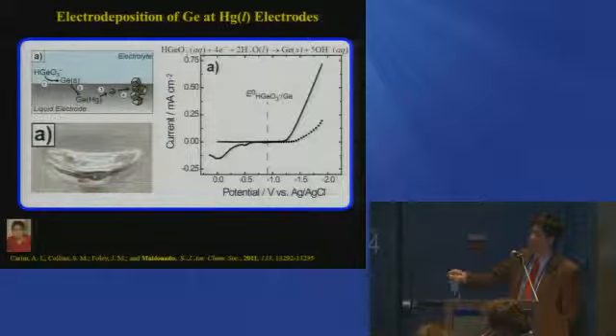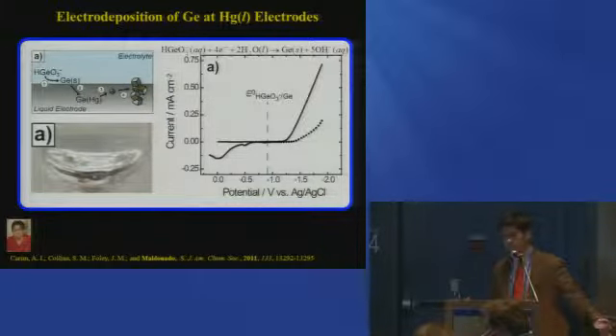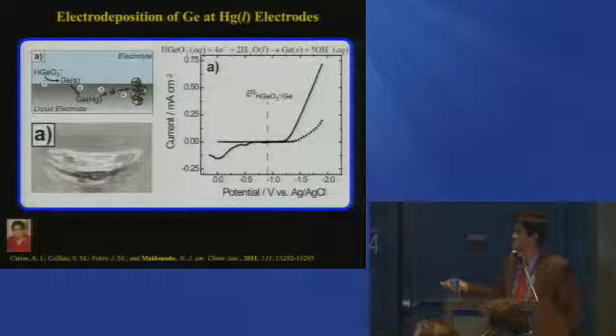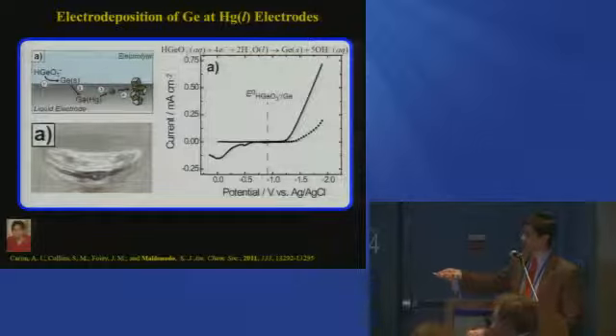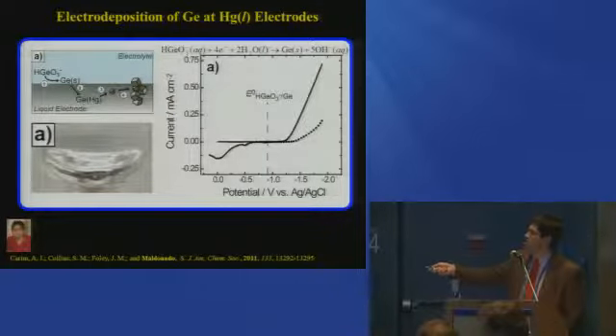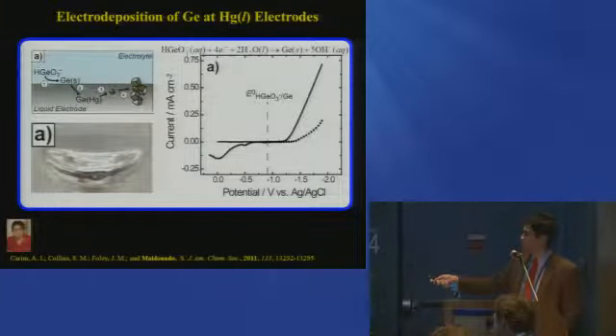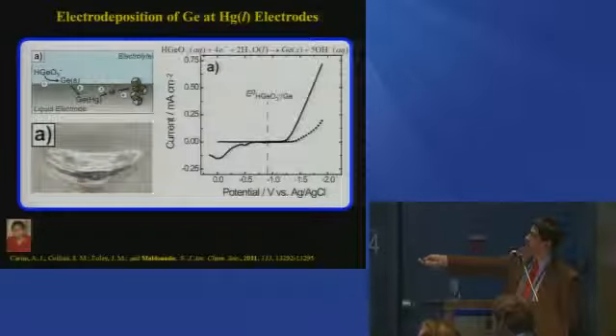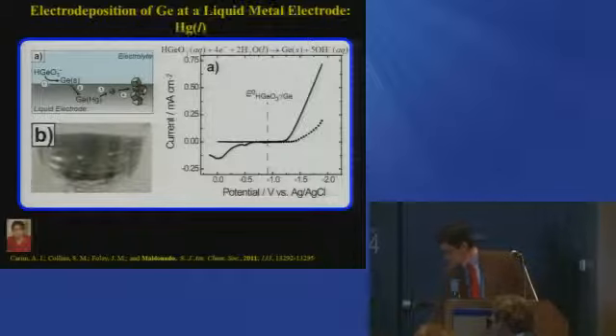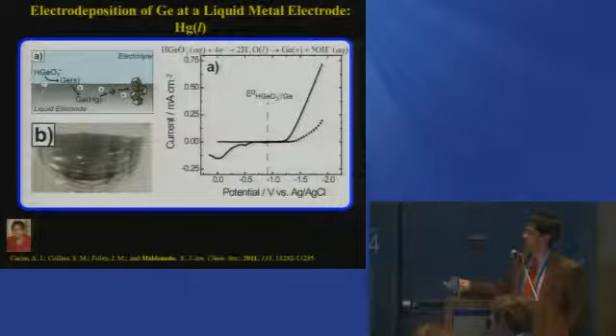If you take this solution now and you sprinkle in some germanium oxide, this is stuff that you would pull out of the ground, the raw stuff, dissolved in this basic solution. The idea that we were trying to push, actually accidentally at first, but now intentionally, is to reduce this germanium oxide to germanium at the surface of this mercury pool electrode, have it dissolve in that mercury pool, and then form germanium crystals. And so this is what the voltammetry looks like when you sprinkle in some germanium oxide. The species at this particular pH is actually this, but it's dissolved germanium oxide.